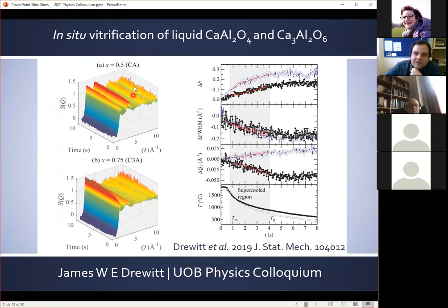And we can actually, at least for the equimolar composition, see an inflection in this change in the supercooled region. This occurs at around 1.25 times the glass transition, which coincides with the so-called dynamical crossover temperature, below which dynamical arrest tends to begin in glass forming liquids. So these fast synchrotron measurements during solidification indicate some substantial changes occurring in medium range order. It's advantageous to use some element selective techniques to probe the aluminium and calcium coordination environments in more detail, to really see what's going on during the glass formation.